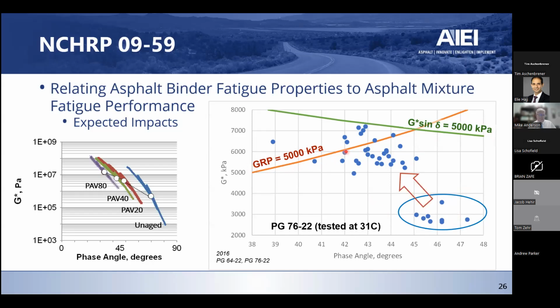This orange line that you see here is the proposed line for the Glover-Rowe parameter. And you can see some differences here. First of all, anything above that is going to be a failure compared to where it was. So some materials that had previously passed might not pass with the Glover-Rowe, particularly as you get to higher stiffnesses and lower phase angle materials. This one is well out there, for instance. It passes easily on G* times sine delta. It would fail easily on the Glover-Rowe parameter.